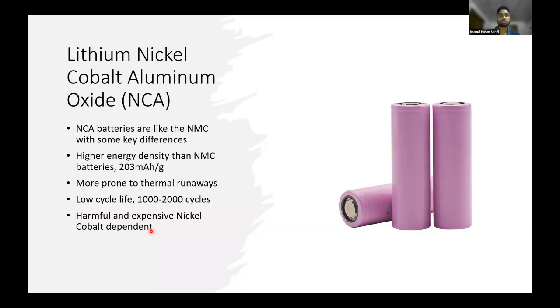That means above 120, 150 degrees, it will go through thermal runaway. And if you saw some accidents in electric vehicles, which sometimes people make viral, those who do not like electric vehicles, you can see that sometimes fire broke out. And this is also because of the chemistry, because some chemistries like this one are not that good for thermal withstandability. So it goes through thermal runaway, and whenever it goes through thermal runaway, fire will surely break out. And that will create a problem.